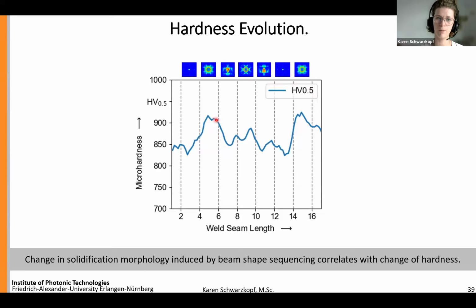So far, it has not been understood why we do see higher hardness values for the columnar oriented microstructure, because from theory we would expect to have lower values here, but we are, as I already mentioned, digging into microstructural analysis based on EBSD to understand better what is going on here.